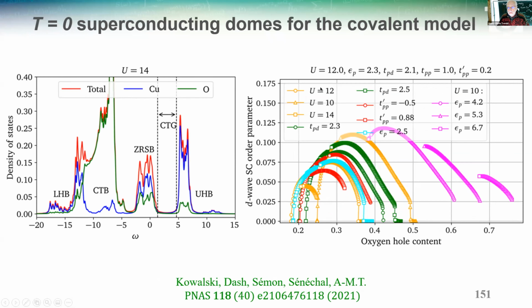Now, as I said earlier, we vary the parameters one after the other. Every time we have a new set of parameters, we have a new material, we change the chemical potential, and we get a superconducting dome. This is the d-wave superconducting order parameter in the ground state, and that's the oxygen hole content. Clearly, the domes here have a larger d-wave order parameter if they have larger oxygen hole content. So the optimal d-wave order parameter comes with a large oxygen hole content.